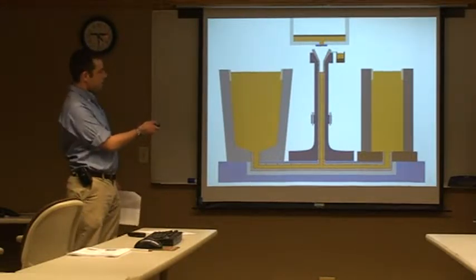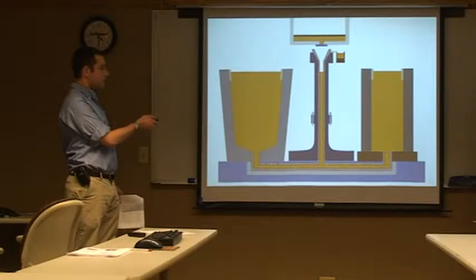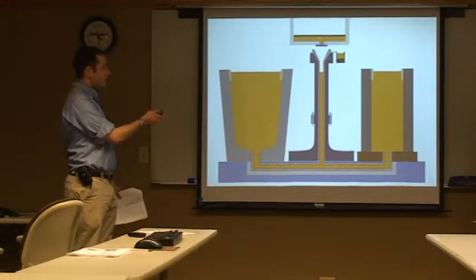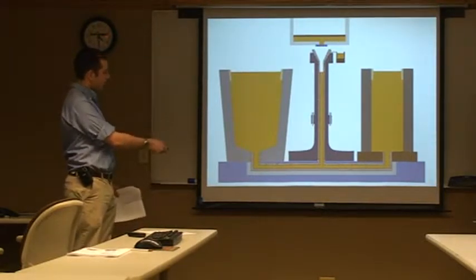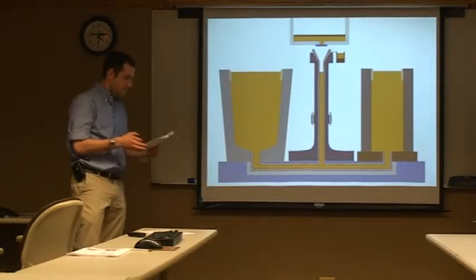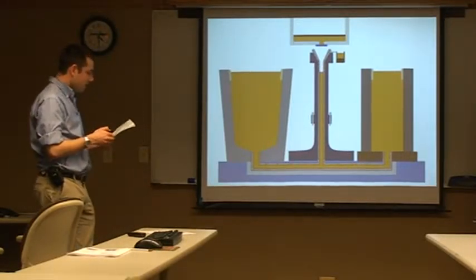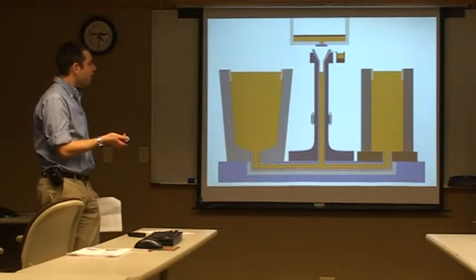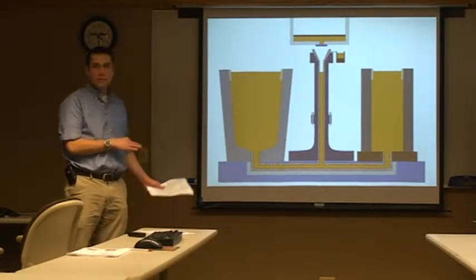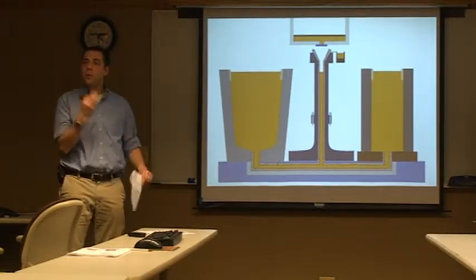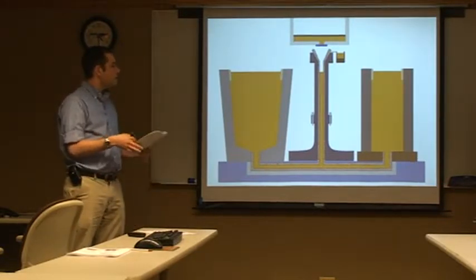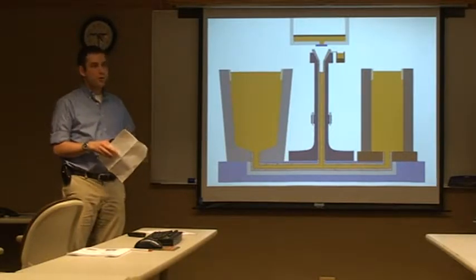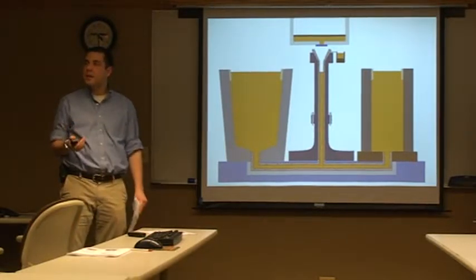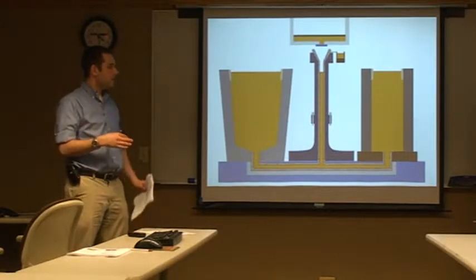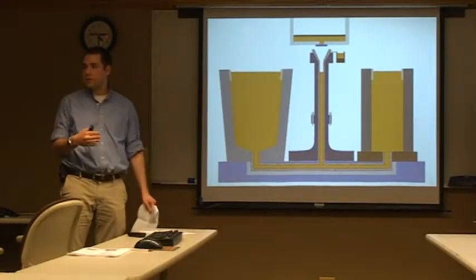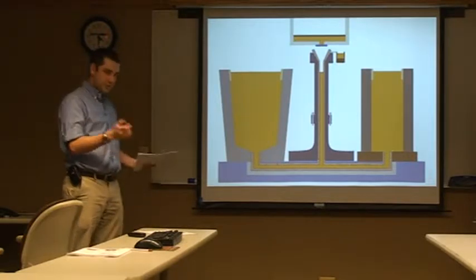And also, you see the steel in the trumpet only gets to that level, which means if we did have any slag coming out, it would stay in this trumpet and wouldn't get up into the ingot molds. After the teeming process, we let the liquid metal solidify, and then we'll strip away the molds like you saw in the video, and the ingots normally go through some sort of thermal cycling to keep from any kind of thermal cracking happening while the steel's cooling down, and then ship them out.